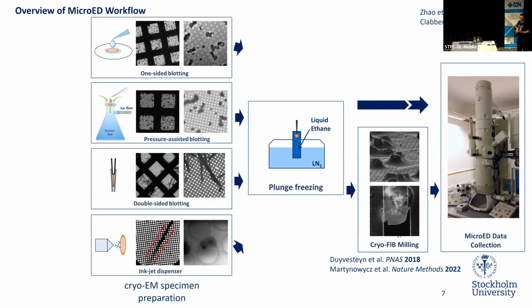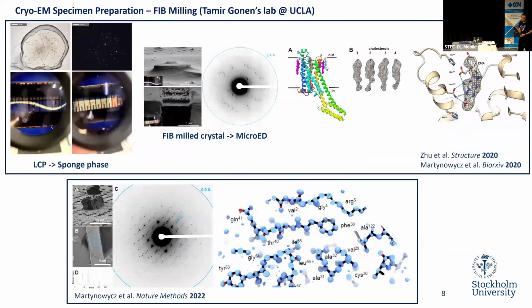And if the crystals are slightly too large, there has been development of FIB milling, which is putting this into an SEM and using gallium ions or other ions to mill a thin lamella from the crystal. And this has very particular use in some cases. From Tamir Gonen's lab in the US, they've shown that it's very useful to study membrane proteins growing in LCP, for example. These are very viscous mother liquor. And then this lipid, and they could mill a crystal lamella from these membrane proteins and collect very nice data from them. And also recently, they've shown that by doing this, they could collect very high resolution data as well. So this is really optimization of sample preparation, right?